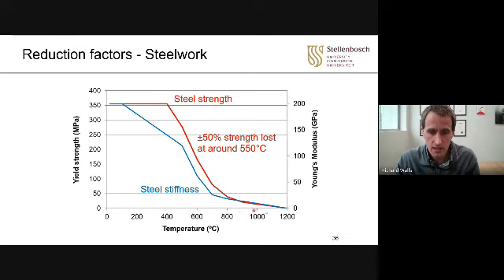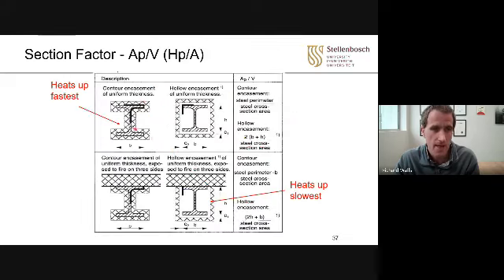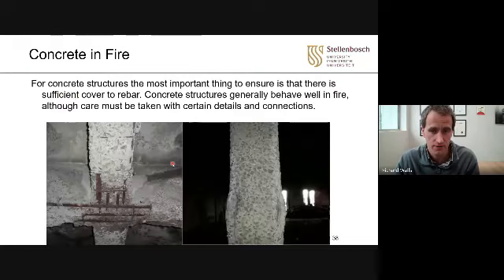So here is then your steel stiffness. What you find is deflections occur. So the stiffness drops first, but then your strength drops afterwards. So it deflects more, but then it also starts getting weaker. So that's your Young's modulus and your yield strength used to measure those. And as I was saying, your section factor, this heats up faster, this heats up slower. So you can also do different layouts to get to different solutions. And this passive protection will be cheaper than that there. Firstly, this is a longer perimeter, and it'll need to be thicker than this one here. The only thing is boards, you have to do a lot more effort, and this can look nice if done properly, but there are pros and cons of all the different systems.